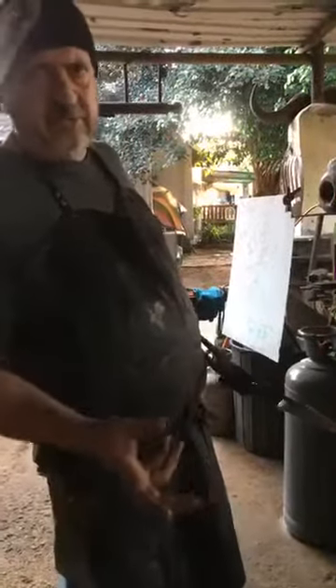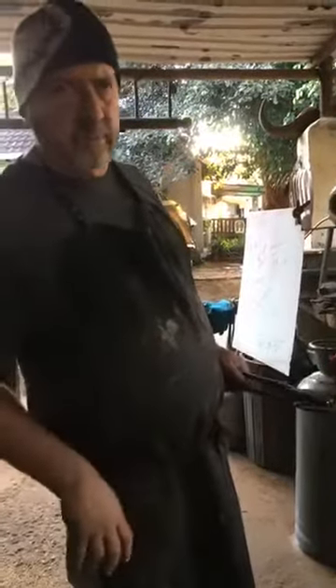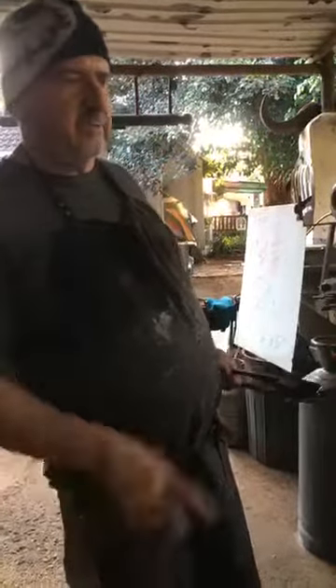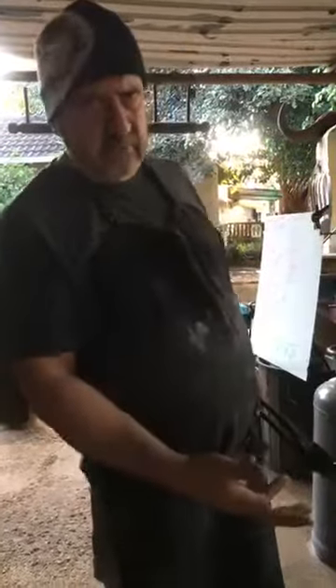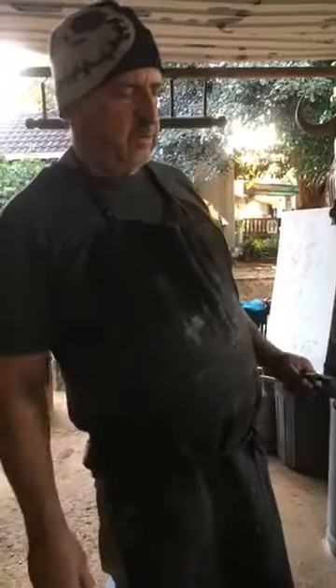So if you have a spare container with oil, stick it in there until it's no longer simmering or bubbling, and then take it out a bit later. And I'm going to go from there, and then into the cold oil, and that should cool it down sufficiently. Then we test it with a file to see if it's catching or not. So let's fire up the forge and do the same.